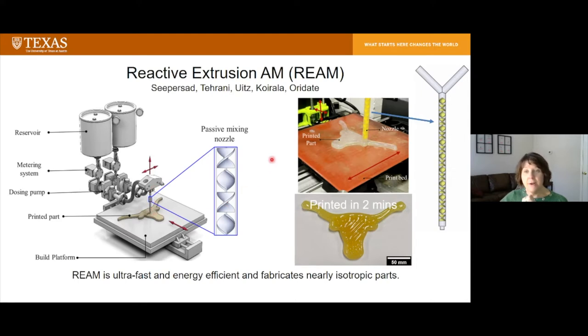And so then they cure very rapidly on the build platform, and that allows us to build parts very, very quickly. It's ultra fast, which I'll show you in a second, and it's very energy efficient, so no external energy is required. And we can fabricate nearly isotropic parts. So here you can see on the bottom right, a longhorn that we printed. It's about 10 inches across, and we printed it in 2 minutes. So let's take a look.